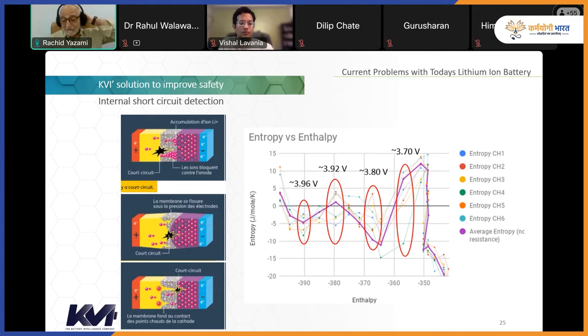So what happens is that dV/dT is in the order of 0.1 millivolt per Kelvin. It's very low, 0.1 millivolt per Kelvin. So in order to do entropy measurements, the voltage should be measured within an accuracy range of 0.1 millivolt. The same for the temperature. The temperature should be measured within 0.1 Kelvin. If we have this, we can do the derivative, dV/dT, and have entropy data.